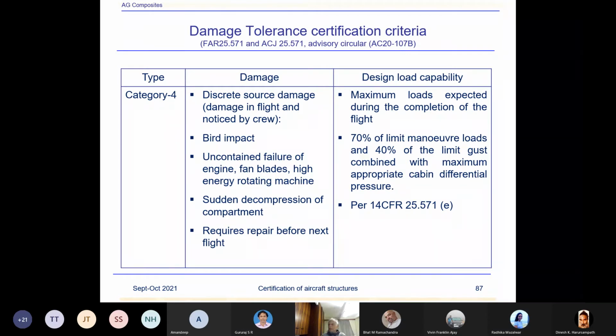So category 4. In that diagram, I said category 4 damage, which is discrete source damage, which occurs during the flight, and the pilot or flight crew knows when it occurs. So the causes of the damage could be bird impact, uncontained failure of engine, fan blades, high energy rotating machine, sudden decompression of compartment, requires repair before next flight. Design load carrying capability, according to the requirement, is maximum loads expected during the completion of the flight and 70% of limit maneuver loads and 40% of limit gust load combined with maximum appropriate cabin differential pressure. Part 25.571(e).